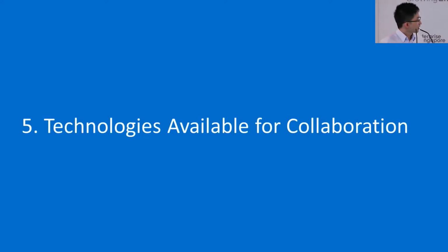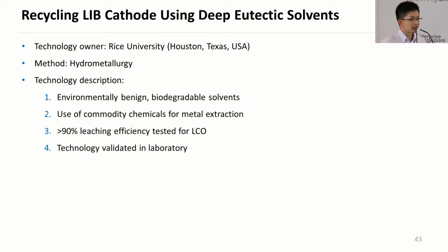For the final section, I will talk about the technologies available for collaboration. So the first one will be from Rice University. They are based in the US. They are using an environmentally benign, biodegradable solvent. It's called deep eutectic solvents. So they are using a mixture of choline chloride and ethylene glycol, both commodity chemicals, to achieve metal extraction. And they have achieved a pretty good recovery rate of more than 90% leaching efficiency. And they have tested this for LCO in the lab.